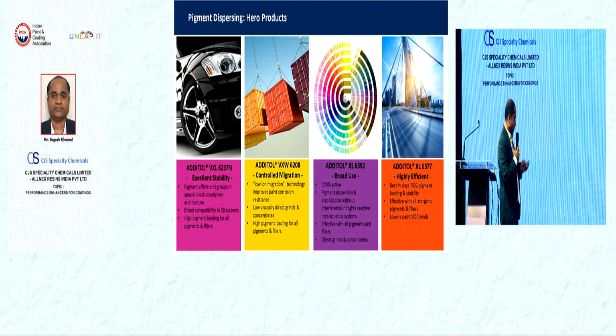this particular system. Then 6592 is again a 100% solvent-free pigment wetting and dispersing agent, especially in non-aqueous solvent-based systems wherever the curing mechanism is very sensitive. From a stability point of view, it gives very excellent stability performance.